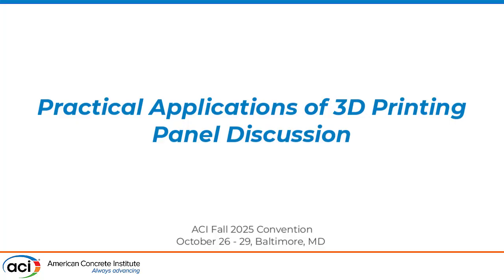Which then, to your point, Jacob, it's almost like now that layer height is taller, you're effectively printing faster. Right? So when we increase from 15 millimeters to 25 millimeters, we're literally going almost twice as fast. And so what are the things needed to get above 25 millimeters? That's where I think, honestly, the nozzles and the work in that field start becoming very relevant. The traditional shape of a nozzle tends to point downward, whereas for layers thicker than an inch in height, the nozzle starts looking almost like an L shape. Being able to play with nozzles allows you to have taller layers, which increases your efficiency drastically, since you're not increasing your layer time. I just want to share this little piece of information that I was able to gather while we were doing our testing. Any questions from these points specifically?